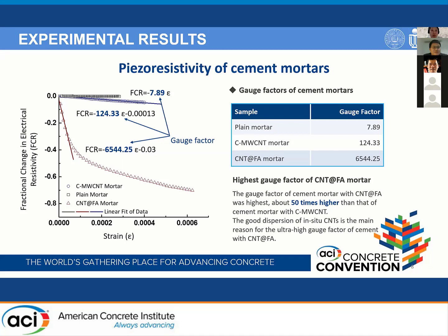From the background, we know that the sensitivity of a cement sensor is usually evaluated by the gauge factor, and the gauge factor can be obtained from the slope of the linear fitting of FCR versus strain curves. After the linear fitting, the obtained gauge factors of these three types of cement mortars are shown in the right table. From this table, we can see that among these three types of cement mortars, the gauge factor of cement mortar made with CNT and FA particles was the highest, even 50 times higher than that of cement mortar made with the commercial carbon nanotubes. And it is believed that the good dispersion of in-situ carbon nanotubes is the main reason for the ultra-high gauge factor of CNT and FA cement mortar.